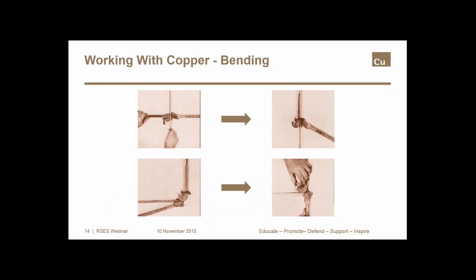The exceptional formability of copper gives us the ability to form it at the job site. When tube is bent correctly, it will not collapse on the outside of the bend, and it will not buckle on the inside of the bend either. We've learned from burst testing that the strength of a bent copper tube can actually be greater than it was before bending. Both annealed tube and drawn tube can be bent with benders. The proper size bender must be used for each size tube.